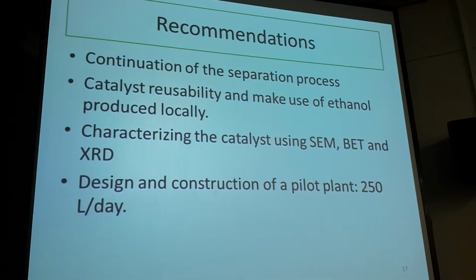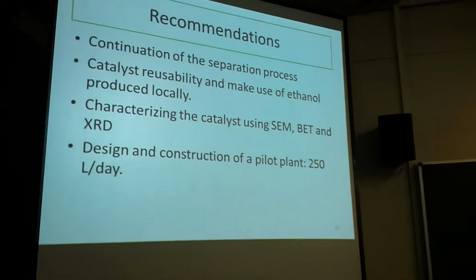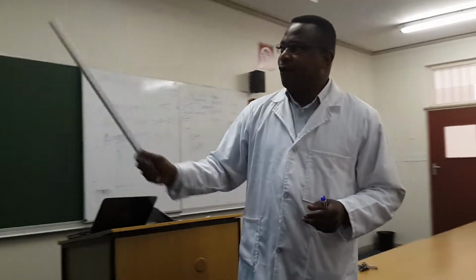And as a recommendation, we suggest that the project might be continued, and this is basically what our friends are currently doing. And the catalyst is supposed to be reused as many times as possible. And also, the samples of your catalyst, we are sending them now to the UCT and Stellenbosch so that they may do the XRD and the SEM to know the size of your particles, and also the BET to know the surface area of the catalyst, because do not forget the activity of your catalyst depends on the surface area.